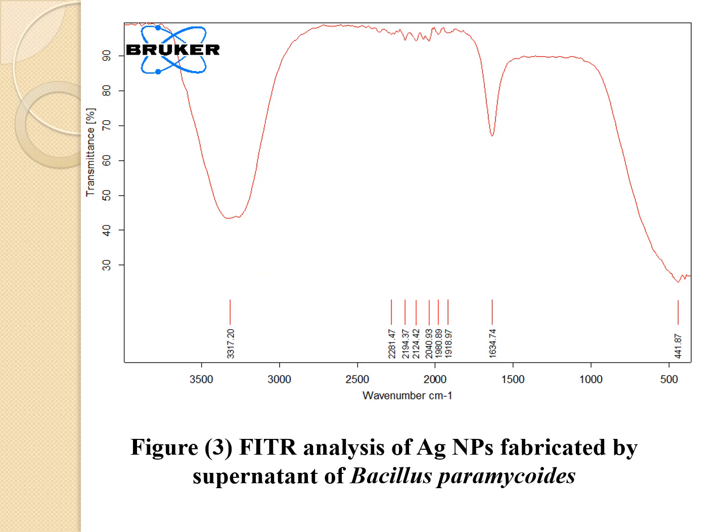This illustrates the FTIR analysis for the silver nanoparticle solution, which showed the presence of a band located in the region between 3344 and 3310 cm-1 that corresponds to the amide group, confirming the presence of protein in the sample. Also, the presence of bands located in the region related to carbonyl, amide, and nitrate. These groups possibly can participate in the fabrication of silver nanoparticles.